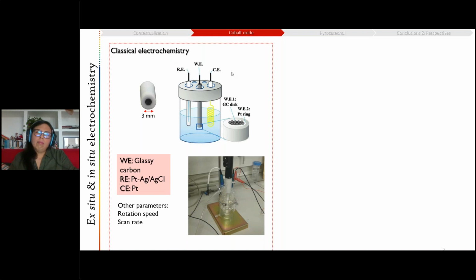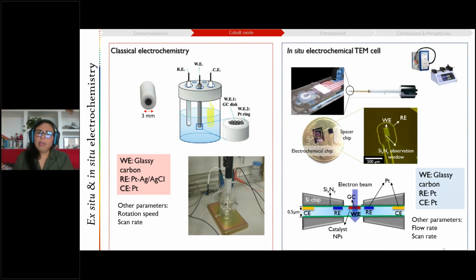So a typical electrochemical cell is composed of a reference electrode, a working electrode, and a counter electrode. And in our case, the materials were analyzed on a glassy carbon disc in a rotatory system. And we have an electrolyte that could be adapted depending on what we were interested in. In our case it was a basic electrolyte, which is potassium hydroxide. And we tested the silver chloride reference electrode, which is, let's say, the most used reference electrode. And we also tested platinum wire as reference electrode in order to be able to compare with our electrochemical cell in situ.